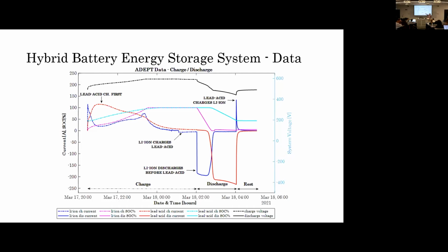So the first thing that discharges is lithium ion. That's exactly the case I was trying to make earlier. If you remember, with the base covered by lithium, the peaks on the top graph will be covered by lead acid. So in this way, you're cycling lithium up and down. You can do many cycles, and lead acid covers only the peak times. Lead acid can't do 3,000 cycles. Well, in this case, it does, but just as an illustration.